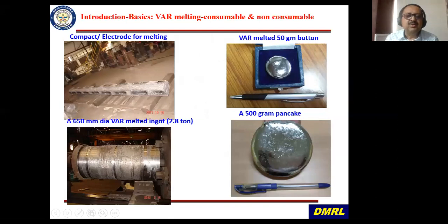Now here I'm just showing you how big an industrial electrode is. This is around 172 kgs. Several compacts were welded together by plasma welding and made into an electrode. And after, let's say, melting several times, this is the kind of ingot that you get, which is around 650 dia. This is a triple melted 2.8 ton ingot, which is getting machined.